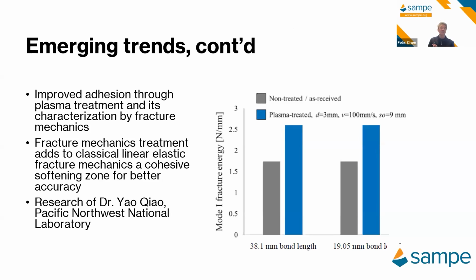Now, the fracture mechanics, in case you're not familiar, there's a conventional one. And then in more recent decades, there's been a move toward a quasi-brittle one, which incorporates a cohesive softening model. One of the features is there is a size effect that affects your results. What his work does here is to take out that size effect and show that the adhesion is independent of the geometry. He's showing that you can increase the strength and adhesion regardless of what delamination size you want. And that's what you need for a better treatment here. This is an extension of the quasi-brittle fracture mechanics work that he has done and that in the literature has become more prevalent in the last couple of decades. But that's a newer extension of the classical fracture mechanics work coming out of George Irwin and Griffith and that work. Next slide.